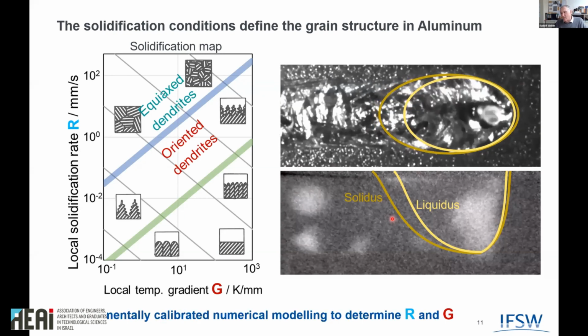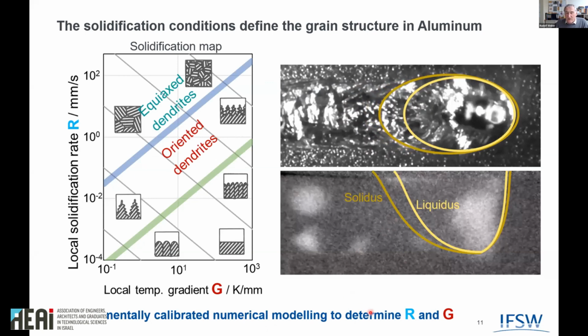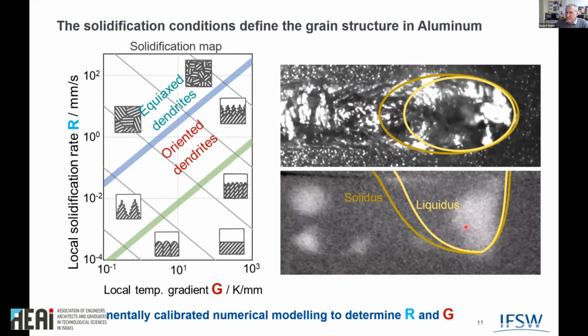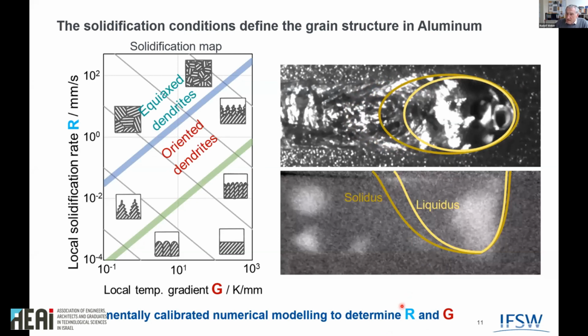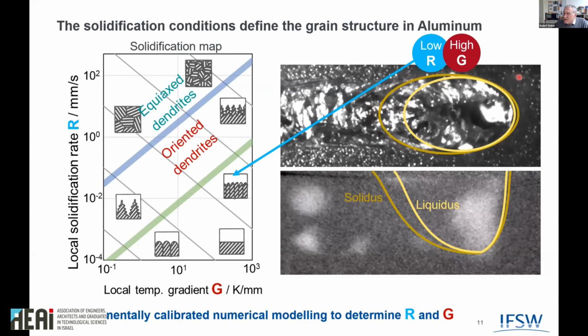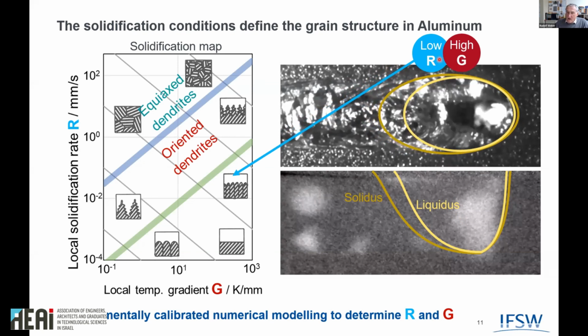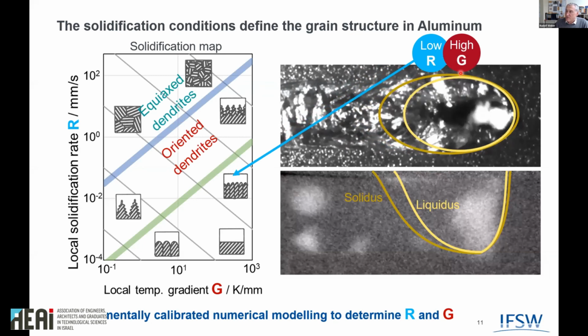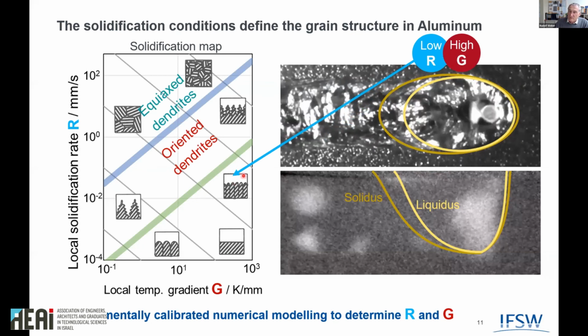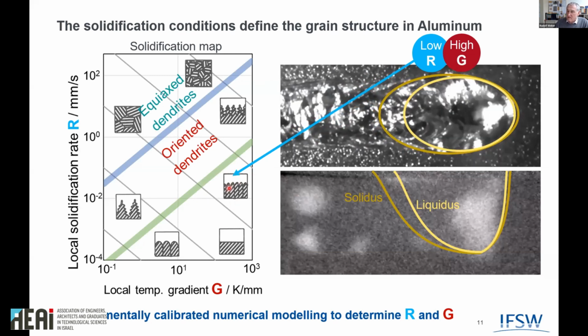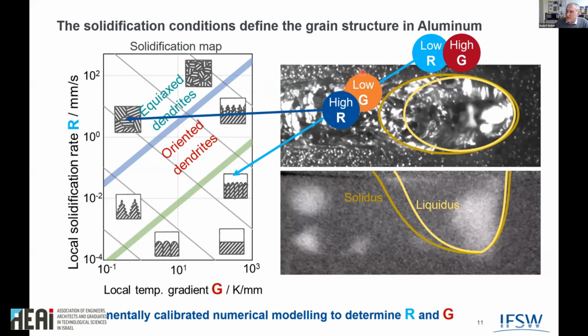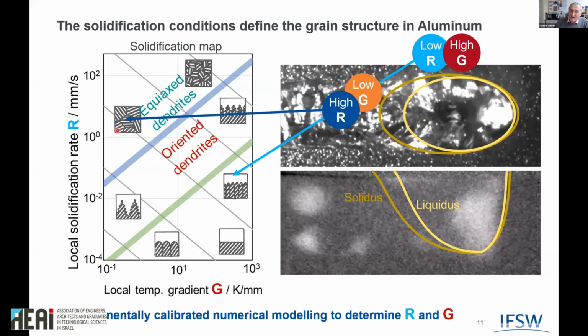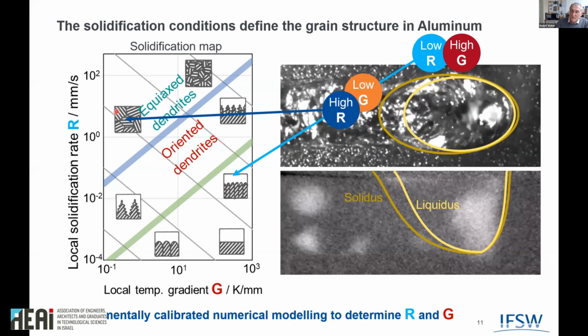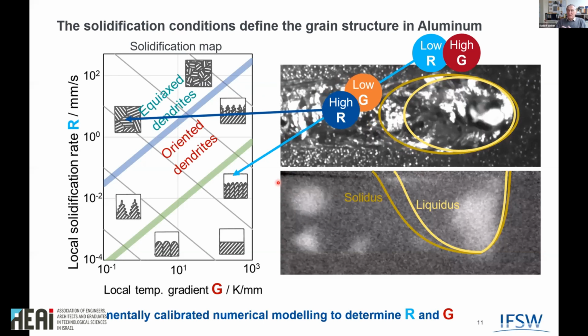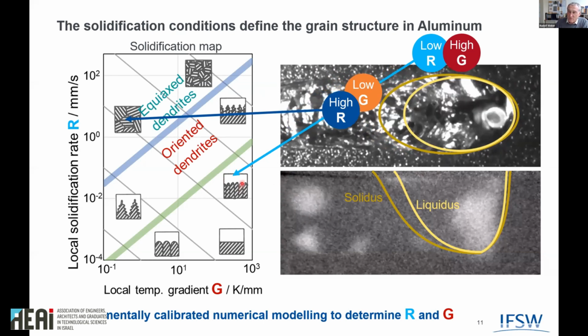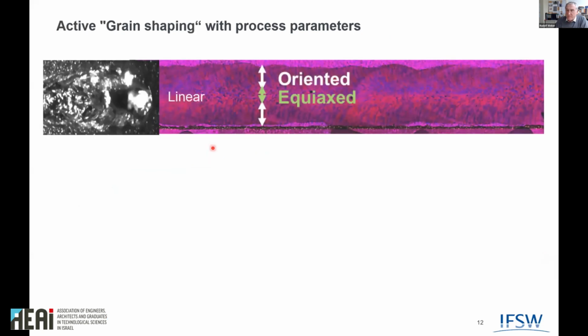And now I want to show that we do some numerical modeling, which we calibrate with these films. And then we can determine the local R and local G. You can easily understand that at the side, we have a low R, which means a low solidification rate, but a very high temperature gradient. So we would end up in this region with the oriented dendrites. At the back of the weld, we have a high R, so a high rate, and a low temperature gradient, so we would end up here. The trick is now to adjust everything and to understand the process parameters to really get here and here. And this can be done.